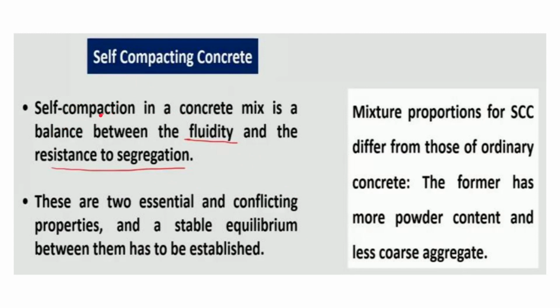Self compaction in a concrete mix is a balance between the fluidity and the resistance to segregation. These two are the main parameters, which can be tested by the four tests we discussed, like the flowing ability, passing ability, viscosity, and one more. Those tests are used for checking the fluidity and resistance to segregation, whether they are at an optimized or adequate level. The fluidity, as we just studied, can be achieved by using the superplasticizer, and the resistance to segregation can be achieved by using the VMA, viscosity modifying agent. So we will see how.